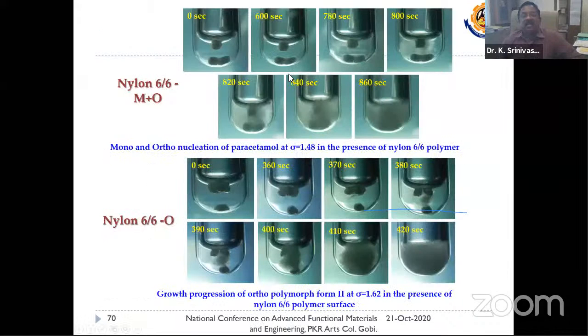And these are all some of the outcomes. See here, nylon 6,6 with the time in seconds. See the polymers and the nucleations. See, needle-like. And this is the mono plus ortho. Both nucleations appear here for this particular condition, where sigma is 1.48, whereas here only ortho conditions, only the needles, started growing. And the supersaturation is 1.62.